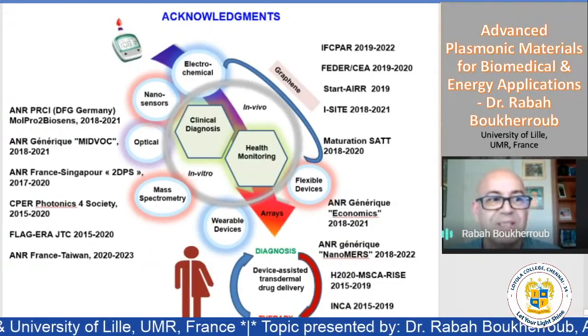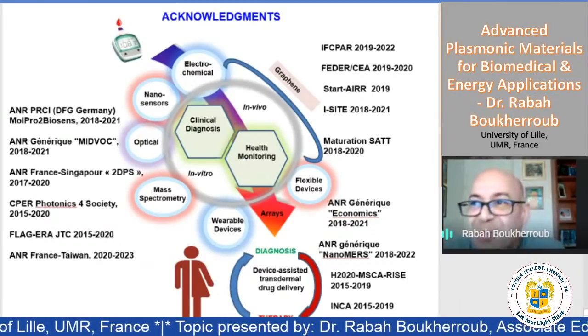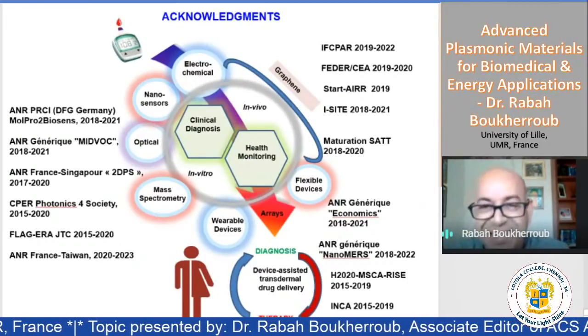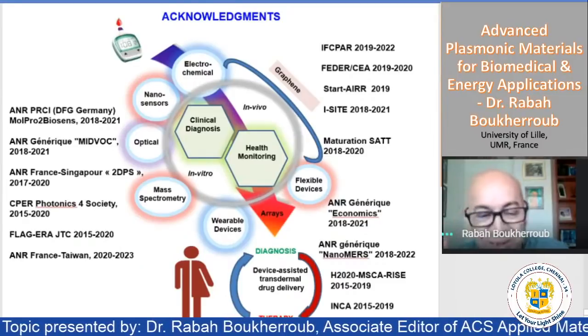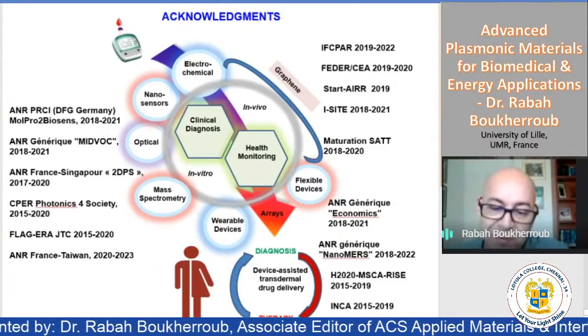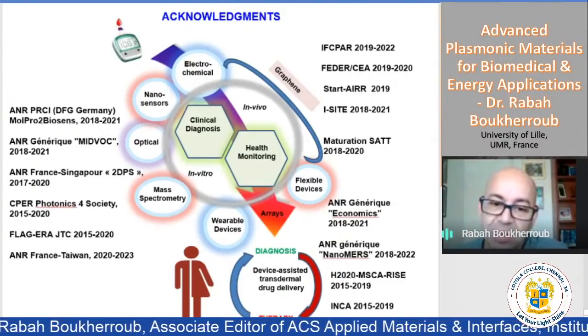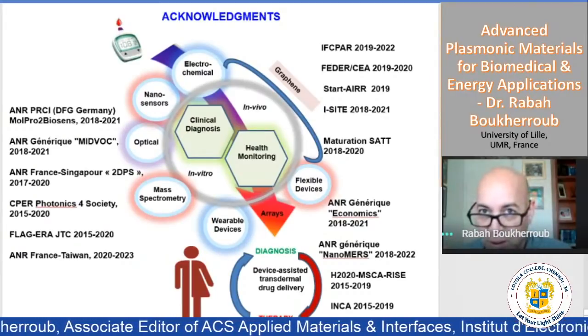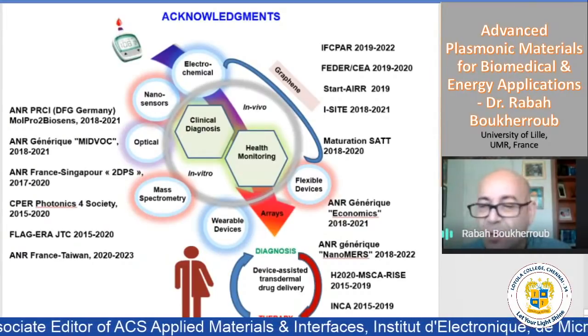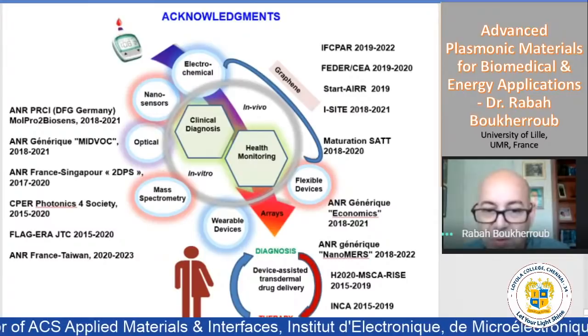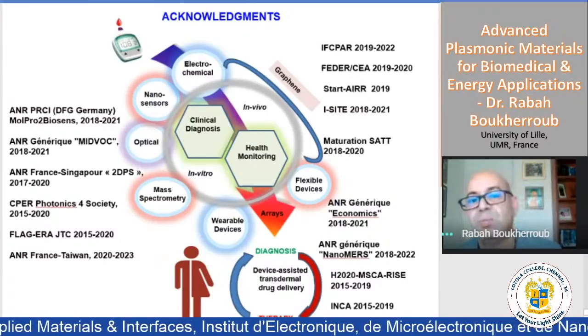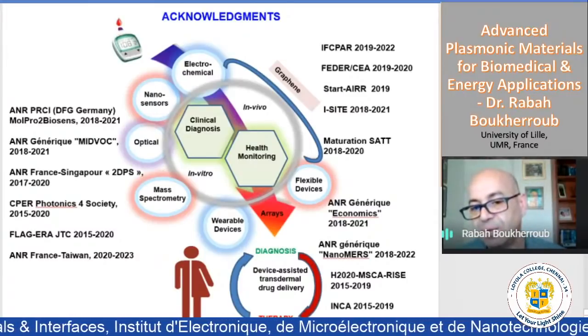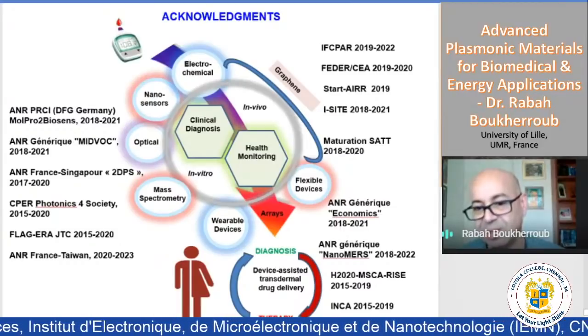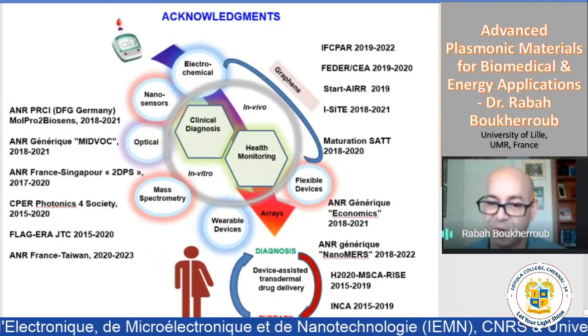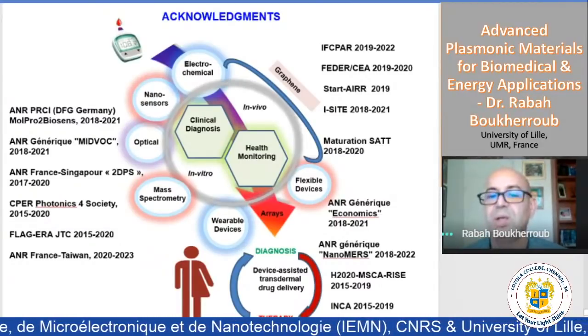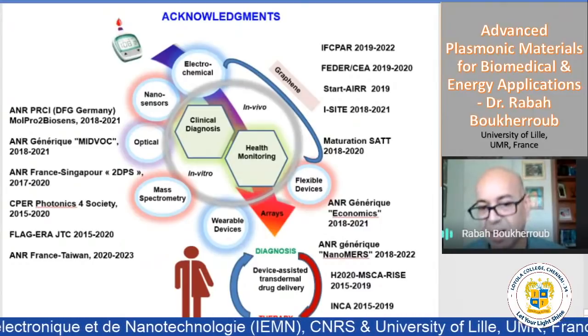To stabilize a single graphene layer, well, if it's on the surface because you grow it, that's not a problem. When you buy the graphene, if it's CVD graphene, it's grown on nickel or copper. On nickel or copper, you have roughly 1 to 2 layers. So that's not an issue. The problem is the graphene you make out of the chemistry. It means you reduce graphene oxide in solution. You have to stabilize that.